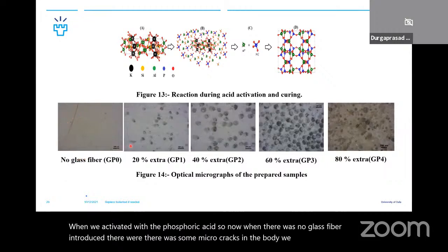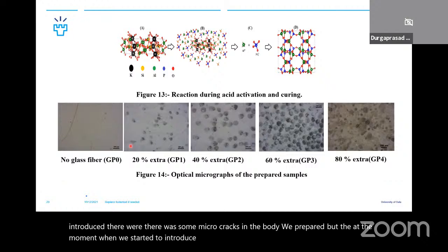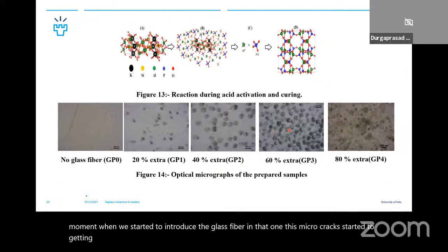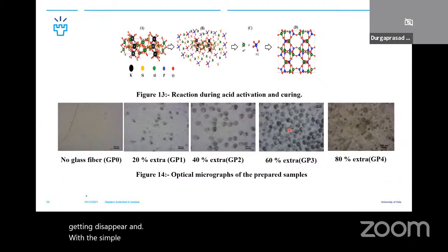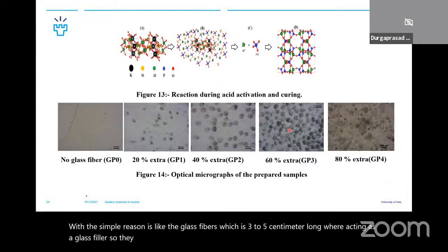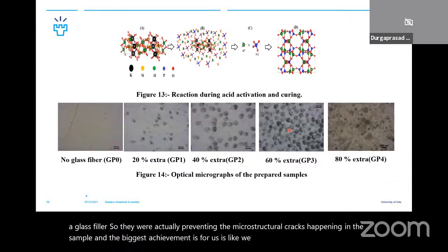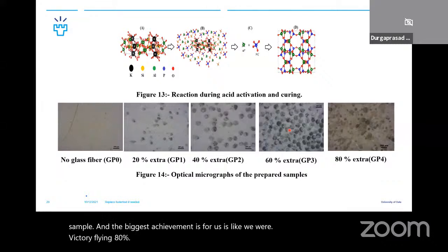But at the moment when we started to introduce the glass fiber, these micro cracks started to disappear. The simple reason is that the glass fibers, which are 3 to 5 centimeters long, were acting as a filler. So they were actually preventing the microstructural cracks from happening in the sample. And the biggest achievement for us is that we were vitrifying 80% extra inorganic waste in that geopolymer matrix.